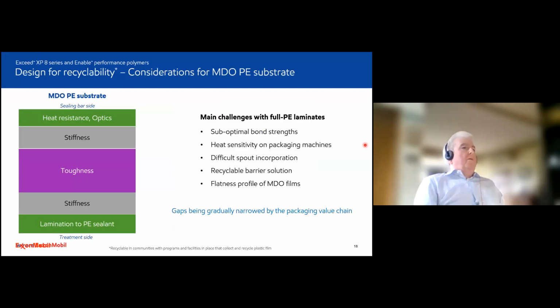So we all know that there are a lot of challenges with full PE laminates, and that's been well discussed by our previous talkers. Things like suboptimal bond strengths. Obviously, the heat sensitivity on the side closest to the sealing bar is particularly difficult to handle when you're using heat sealing bars. Sometimes the spouts can be difficult to incorporate. Recyclable barrier solutions are always a problem.